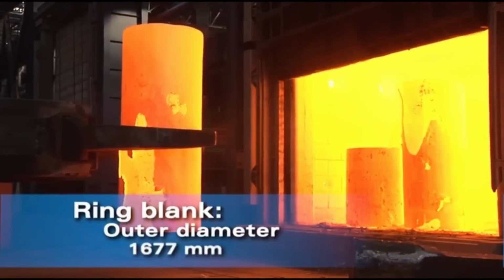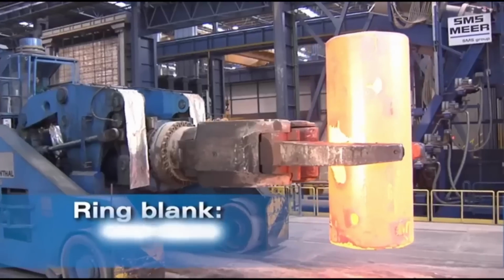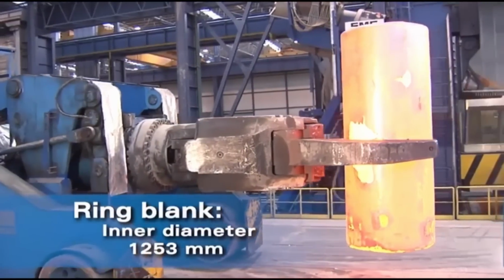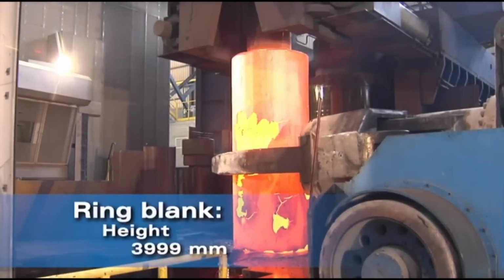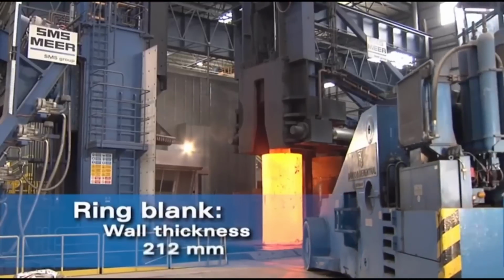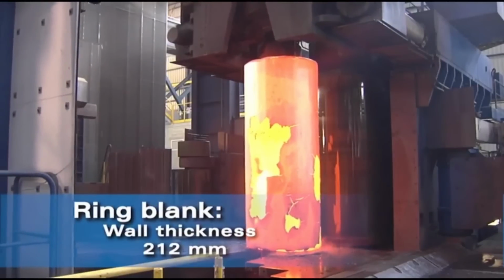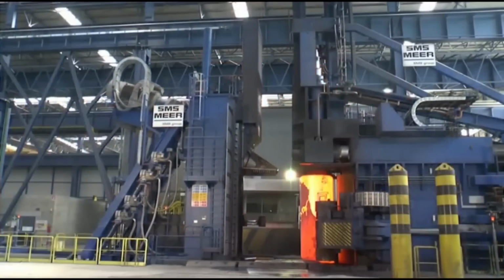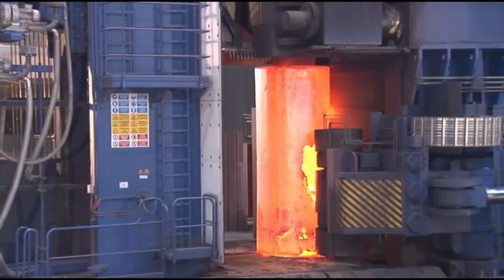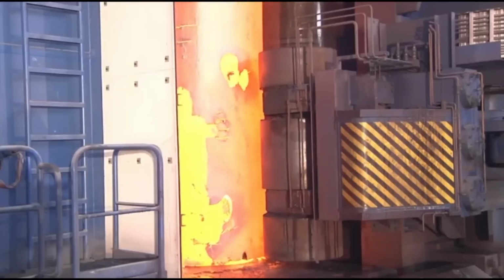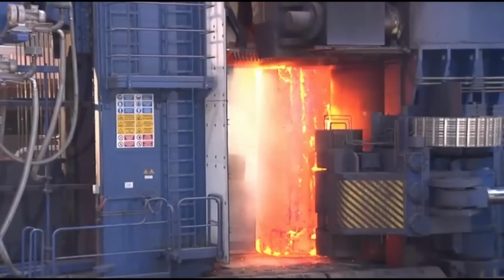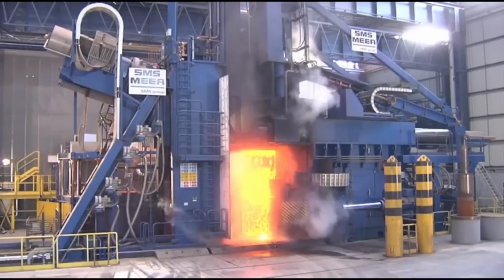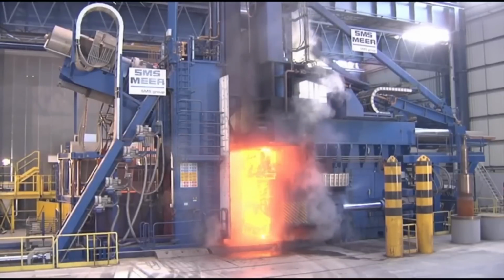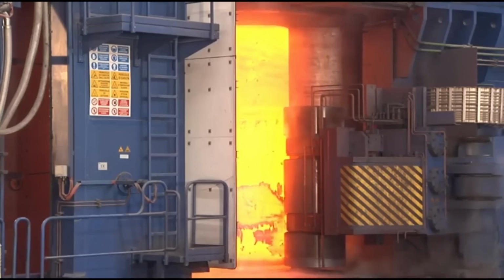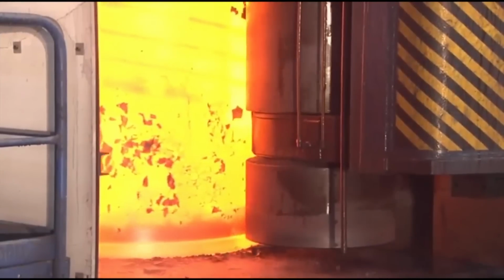A ring blank with an outer diameter of 1,677 millimeters, an inner diameter of 1,253 millimeters, a height of 3,999 millimeters, and a wall thickness of 212 millimeters is processed through the radial-axial ring rolling machine. The machine applies radial pressure to reduce the wall thickness from 212 millimeters to 173 millimeters, while simultaneously expanding the ring's outer diameter to 1,871 millimeters and its inner diameter to